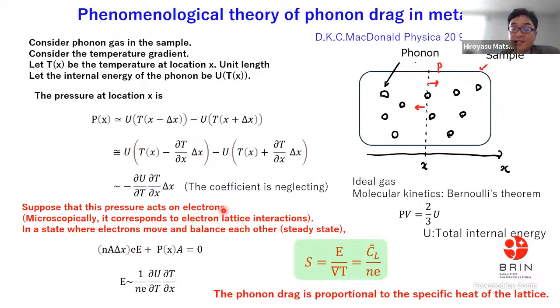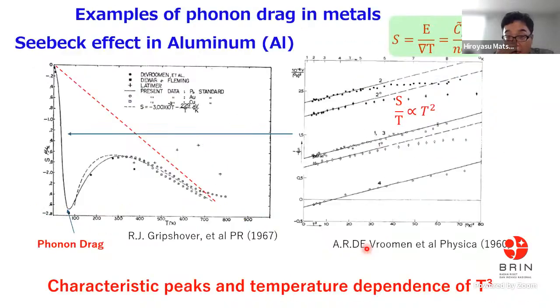So the essence of phonon drag is, okay, in the metal case, phonon drag is expressed by these equations. So S_g is proportional to the specific heat of the lattice. This C_L means the lattice specific heat. Maybe you know that the lattice specific heat is proportional to T cubed at low temperature. Therefore, S_g is proportional to T cubed. You can imagine. So indeed, we can obtain the T cubed behavior in, for example, aluminum.